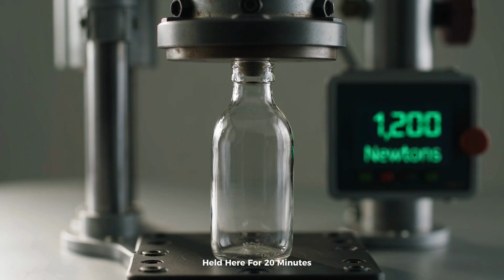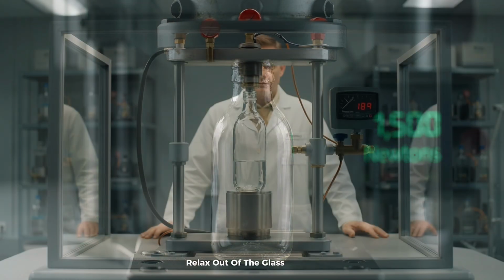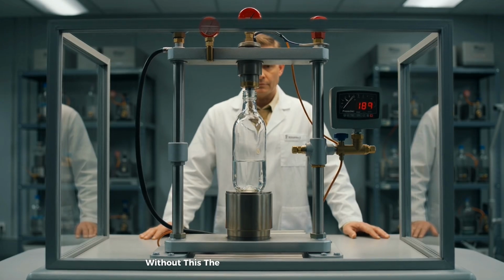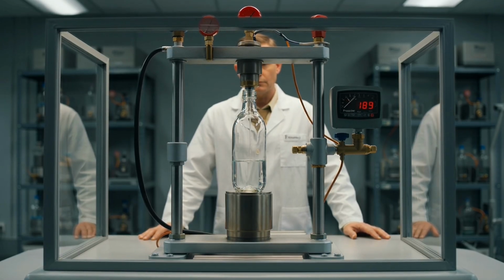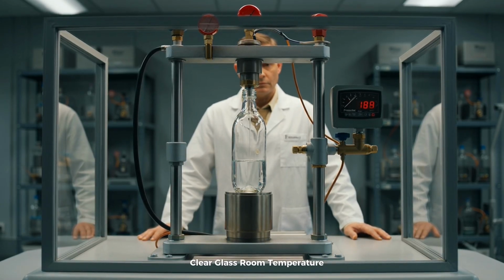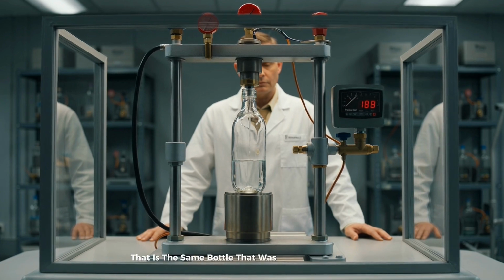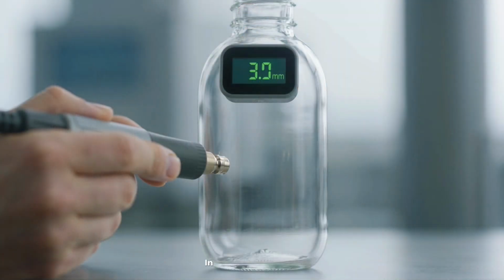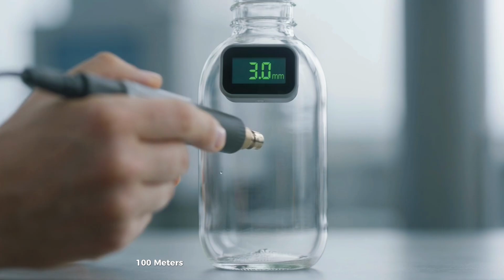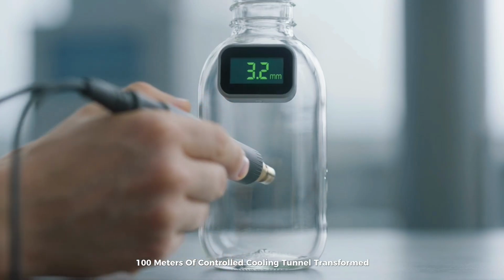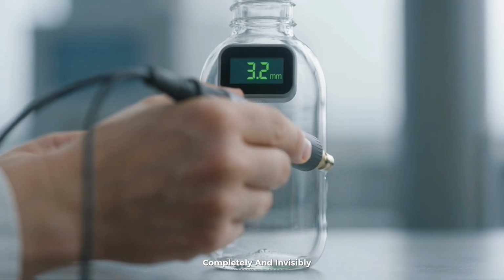Held here for 20 minutes, the internal stresses from the forming process relax out of the glass structure. Without this, the bottle would shatter when filled. Clear glass. Room temperature. That is the same bottle that was glowing red-orange 20 minutes ago in the forming machine. 100 meters of controlled cooling tunnel transformed it completely and invisibly.